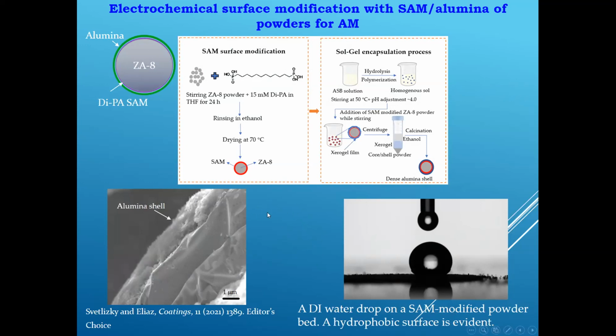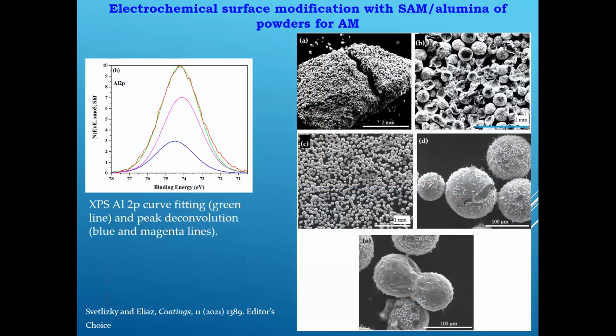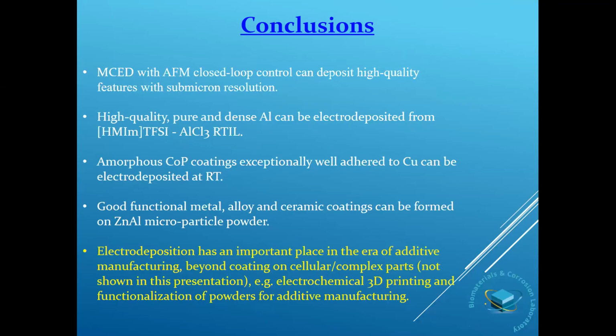And this is already, by the way, I forgot to mention that I already moved to an alumina shell. So this is no longer a metallic shell. And finally, just to show you a thermal stability comparison. On the left side, in A and B, you can see the powder before we applied the alumina shell. We exposed it to a thermal stability test of 600 Celsius for 1 hour in an air furnace. After we apply the alumina shell, you can see for the same batch of powder that you no longer see the agglomeration and sponge formation.